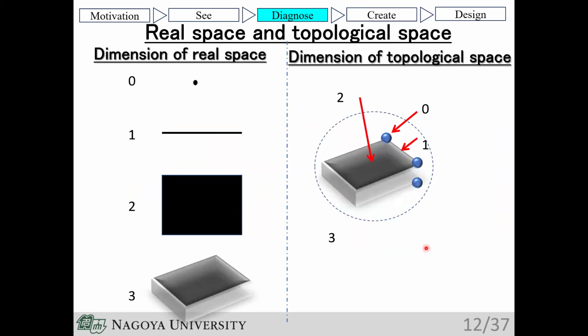Here I explain the topological descriptors and the spatial distributions. In material characterization, metric features related to length scales, such as grain size and volume fraction, are standardly quantified. However, these alone are often insufficient for comprehensive structural description. Critical properties are frequently governed by topological features, including particle count, connectivity, and dispersion.